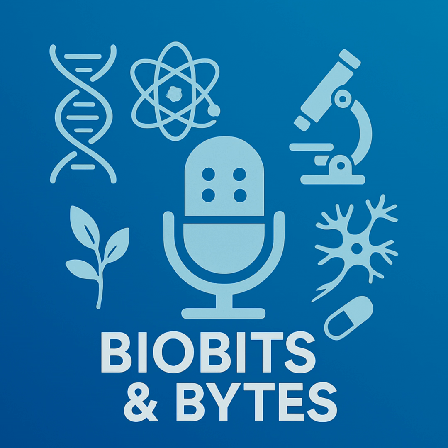And I think you mentioned this heating could do double duty. Yes. If the nanoparticle is designed with a temperature-sensitive coating, or if the drug itself is loaded in a way that it's released by heat, then the same AMF signal that helps open the BBB could also trigger the release of the drug payload once the particle has reached the target area. That's very neat. Open the door and drop off the package with one signal. Potentially, yes. The sources show research exploring both effects.